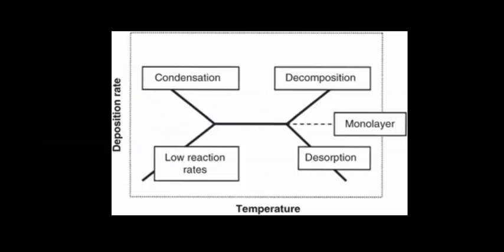All gases will physisorb a self-limiting monolayer under the correct temperature and pressure conditions, even if they do not chemisorb. The preferred conditions are low pressure and moderate temperatures. In ALD, neither temperature nor flow uniformity are of great importance in determining the quality of the films formed. As long as the temperature lies within the temperature window, the uniformity of the local temperature on the substrate surface should not influence film characteristics.